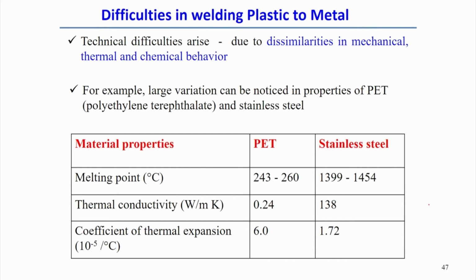Therefore, we can take an example. Suppose there are two materials, PET and stainless steel, and we want to join these two, one being the plastic and the other the metal, stainless steel. Here we can see there is a huge difference in the melting point temperature. One is 243 to 260 degrees centigrade, the other is around 1400 degrees centigrade. Thermal conductivity also has a huge difference, one is 0.24, the other is 138. Then there are the thermal expansion coefficients: one is 6 into 10 to the power minus 5, the other is 1.72.